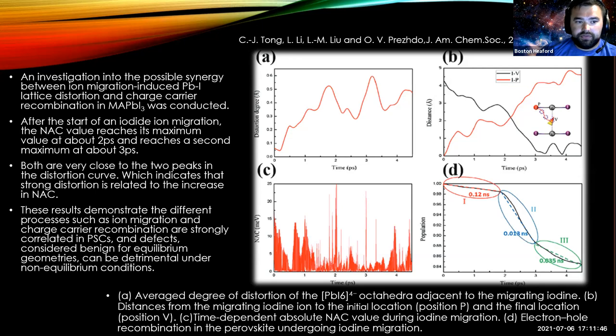And the results demonstrate that the processes are strongly correlated in perovskite solar cells. And defects considered benign for equilibrium geometries can be detrimental under non-equilibrium conditions as the defects migrate through the system.